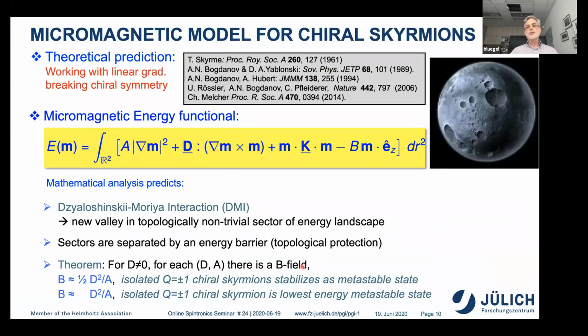So basically, I told you also mathematicians think about these skyrmions, and I'll make it very short. Basically, what one can say about them is, suppose your magnetic anisotropy is not equal to 0, and you have a finite magnetic field, then at the minimum of the energy you can always find a skyrmion. If you have Dzyaloshinskii-Moriya interaction, you can always find a skyrmion at an appropriate B field. So whenever there is a Dzyaloshinskii-Moriya interaction around, you also know there exists a B field which will finally lead to a skyrmion.